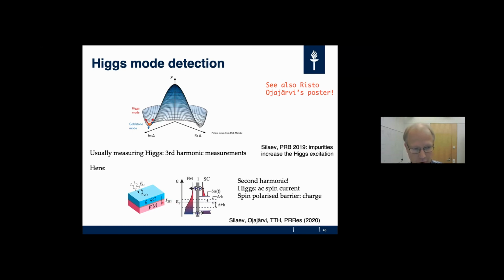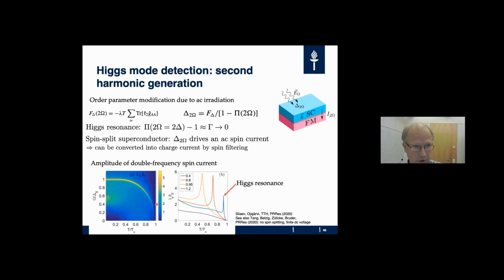If you couple the system via polarized spin tunneling to a ferromagnet, you can also couple it to an AC charge current. The details are given by Risto in his poster, but basically the idea is to get the Higgs mode from the self-consistency equation, which solves a so-called polarization operator, and the Higgs resonance is actually the pole of this polarization operator.